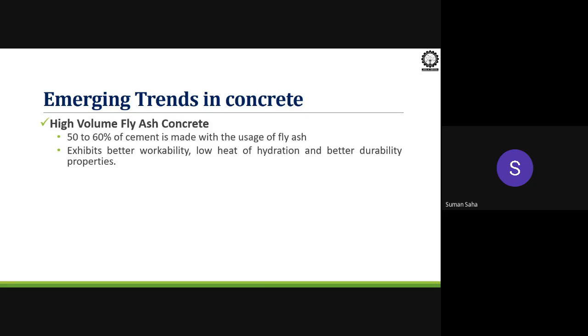And as fly ash is a finer material, it will provide better workability. When the cement quantity is reduced, the heat of hydration will also be low. As a result, we can avoid water evaporation due to the heat of hydration. We may not have cracks at early times, and it can provide better durability properties. Durability can be checked through performance against acidic environment, alkaline environment, or in sea water, salt water. A lot of tests are explained in the different Indian guidelines, which we can follow to determine these properties.